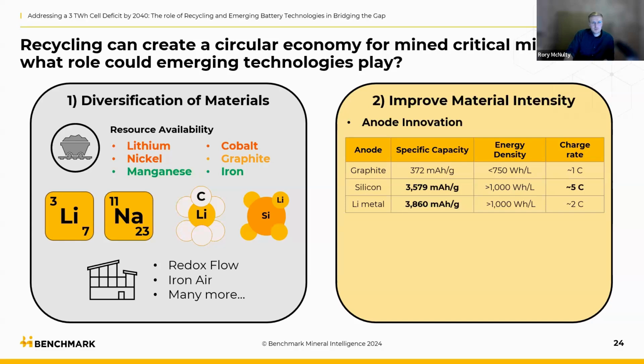Looking at it from a graphite perspective, graphite has a specific capacity of around 372 milliamp hours per gram. That's theoretical, and in the same vein, when you look at silicon and lithium metal, the theoretical capacity is about 10 times higher. Now, in a practical setting, it's more like 2 to 3 times that is likely to be achieved in the near to midterm, but still some really quite significant improvements over those traditional graphite technologies.